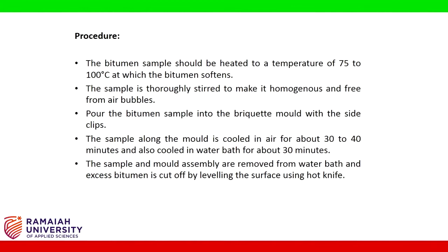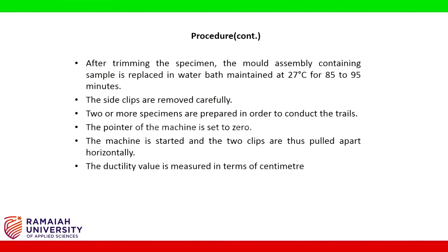Pour the bitumen sample into the briquette mold with the side clips. The sample along with the mold is cooled in air for about 30 to 40 minutes and also cooled in a water bath for about 30 minutes. The sample and mold assembly are removed from the water bath and excess bitumen is cut off by leveling the surface using a hot knife.